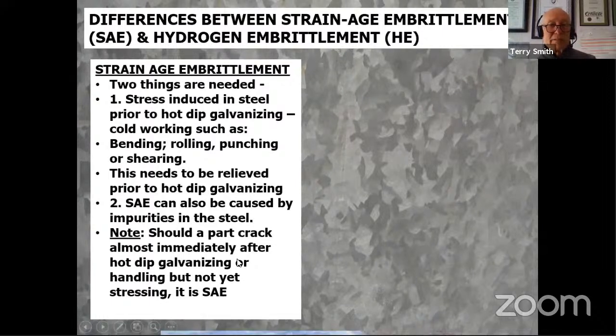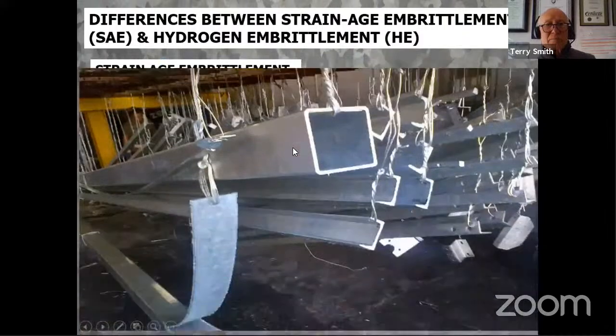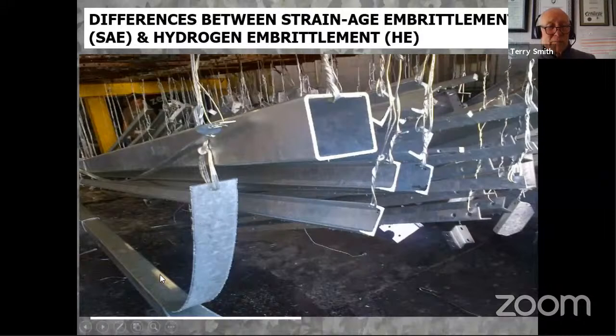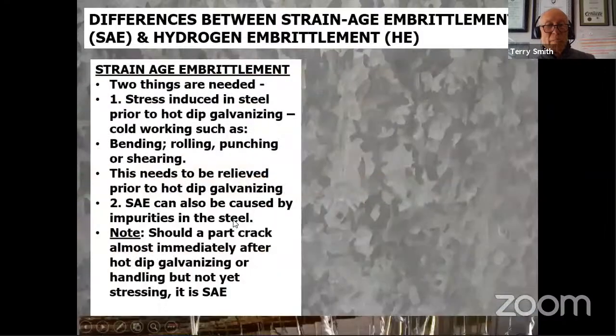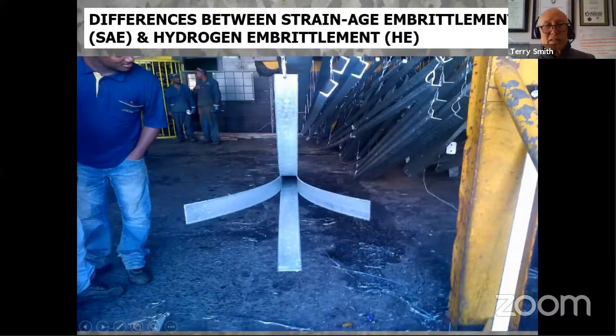but not yet stressing, it is strain age embrittlement. And here's an example of it, and I'll show you various things of this and the reason why. You can see this crack in the steel after hot dip galvanizing. Here's another one. This one's a little bit out of the picture, but you can see this square tube here is perfectly hot dip galvanized without a problem, but this one has a problem. And you can see another view of it. It looks like a crocodile mouth. And what we did in the investigation, we found that